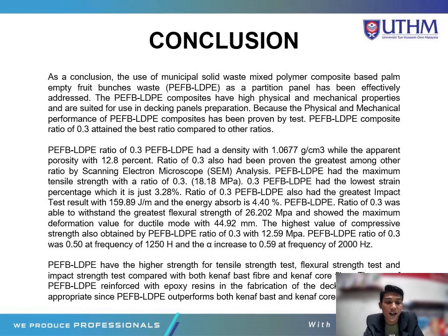PEFB has the highest strength for tensile strength test, flexural strength test, and the impact strength test compared with both Kenaf bast and Kenaf core. The use of PEFB LDPE reinforced with epoxy resin in the fabrication of decking panel was appropriate, since PEFB LDPE outperformed both Kenaf bast and Kenaf core mechanically and physically.